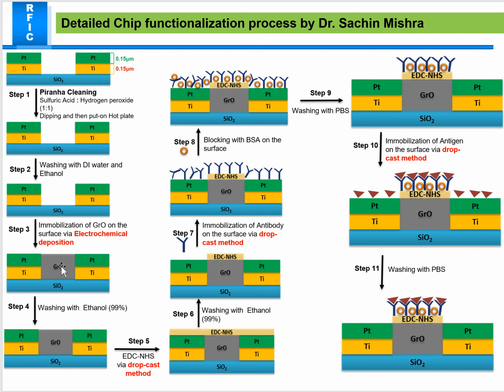And then afterwards we use EDC NHS for the drop casting. If we use drop casting, there is a chance it deposits onto the platinum surface too, but after washing with ethanol, the EDC is only bonded with the graphene oxide. Then we put the antibody immobilization via the drop casting method. The antibodies overflow onto the whole surface area, and so does the BSA, but after washing with PBS, the content on the platinum is washed out from the surface. Only the active part with EDC NHS and the antibody sticks there.